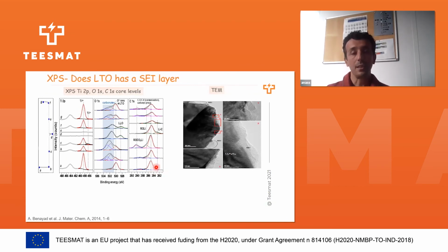To understand the chemical structure of this SEI, we probe the oxygen and carbon peaks at different states of discharge and charge. What we see when we probe the carbon is that during discharge, we observe the presence of some alkyl lithium carbonate groups and the presence of Li2O when we probe the oxygen peak. At the end of the charge, the lithium carbonate peak disappears, which confirms the dissolution of the SEI. Some TEM analysis has proven this process, and we can see that at the top of LTO, we have a thin layer of SEI, which is about 5 nanometers.